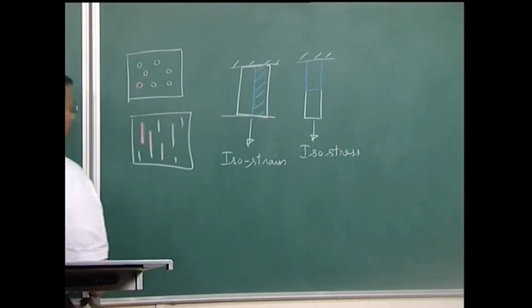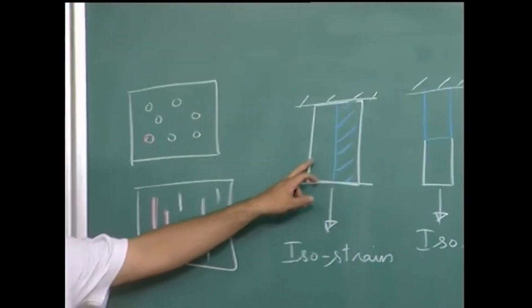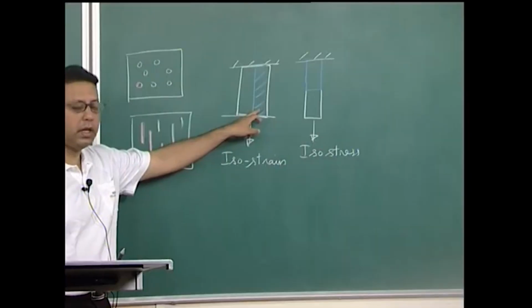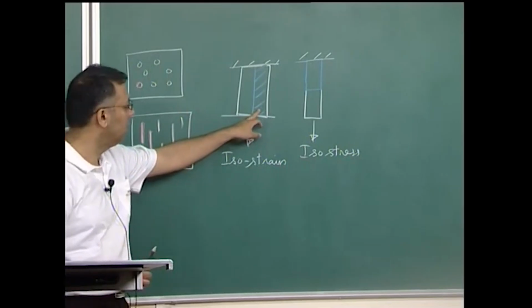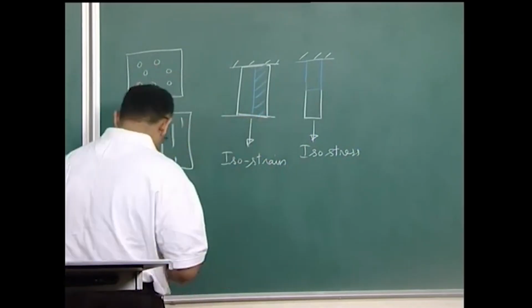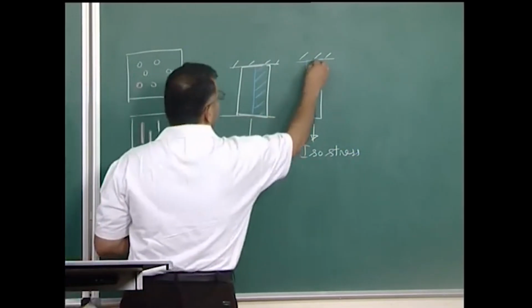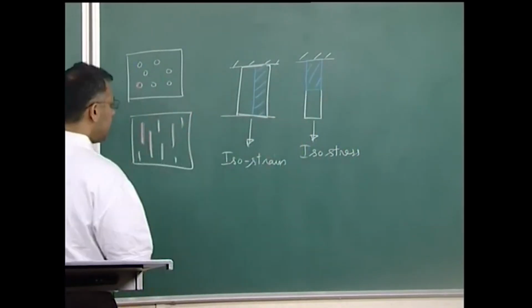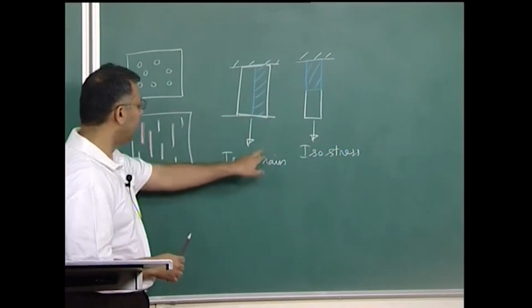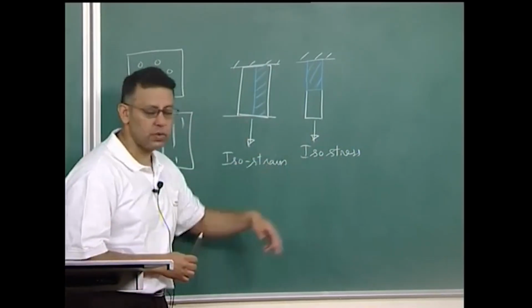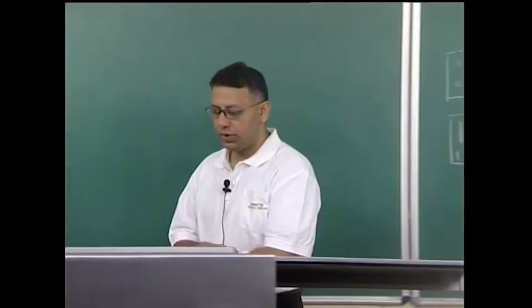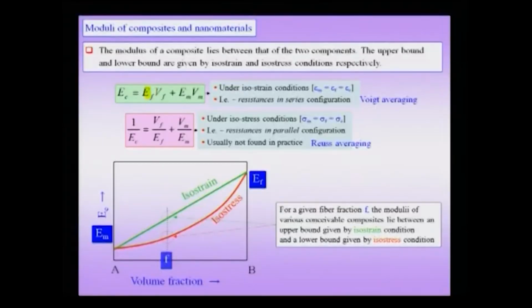So, I can think of two configurations, wherein the matrix and the fiber materials are in a parallel configuration. Another possibility is that the matrix and fiber are in a series configuration. The parallel configuration is like an isostrain configuration, and the series configuration is like an isostress configuration, and therefore, using either one of these two configurations, I can calculate the modulus of the composite given the individual moduli of the fiber and the matrix.